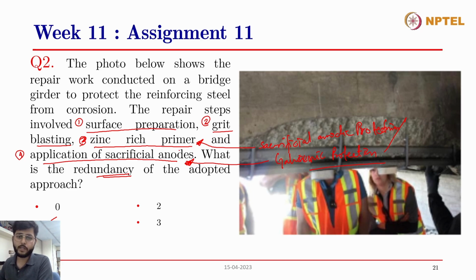It will act accordingly, it will provide the current accordingly, and therefore it will let the zinc anode corrode at a pace which is required by the concrete to protect the rebar inside. However, in case of a zinc rich primer, it is not a properly designed sacrificial anode cathodic protection system, or SACP system.